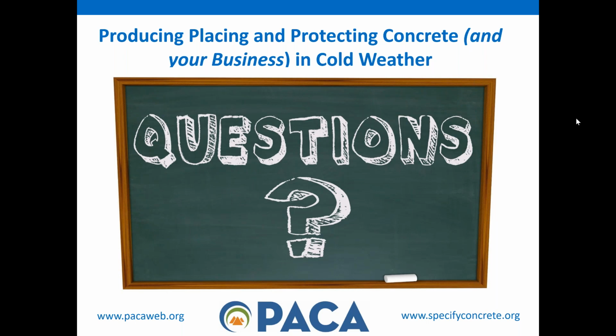Great question. Depends when it froze. If it's able to get some strength before it freezes, you might be okay. What they found is that concrete can withstand one freezing and thaw cycle with not much strength, say 500 to 1,000 psi. Some recent research said it should not be subject to repeated freezing and thawing cycles till it reaches 4,000 psi. So it really depends where and how quickly it froze. If it froze early, you're in tough straits. If it froze later, it should be okay.